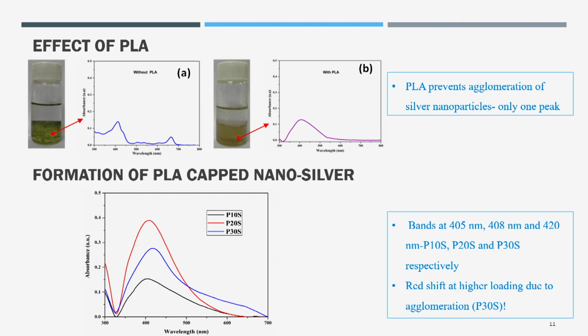All of them are with the PLA, all of them give only a single signal. But slightly, when the PLA amount increases, a slight redshift happens, because initially when 10% of the system, P10S, was scanned, 405 nanometer was the peak. Then the peak increased slightly to 408, not significant, but then 420 was there.